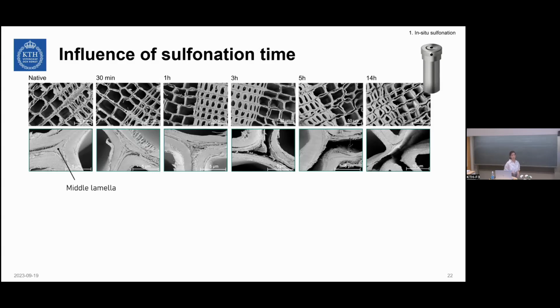So what happens when we push sulfonation is that we have a progressive erosion of the mid-lamellar region, which is lignin-rich. However, even if we push sulfonation for 14 hours and we see a lot of erosion in the mid-lamella, still the cellular structure of wood is not undermined. We could also see that there is a progressive decrease in lignin content from around 29% in native wood down to 15%. So in any case, we're still keeping inside the structure at least half of the native lignin content.